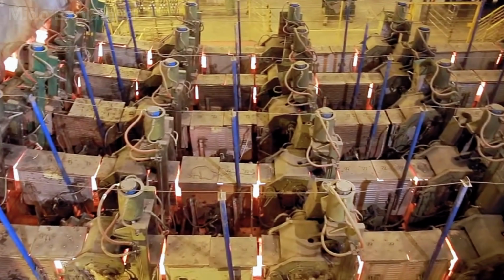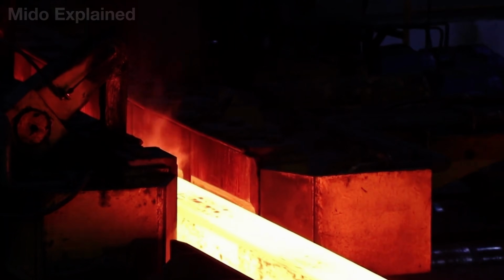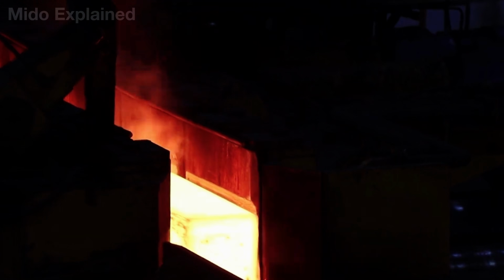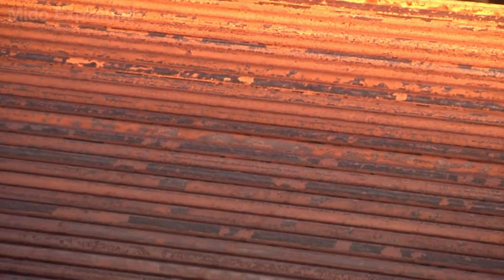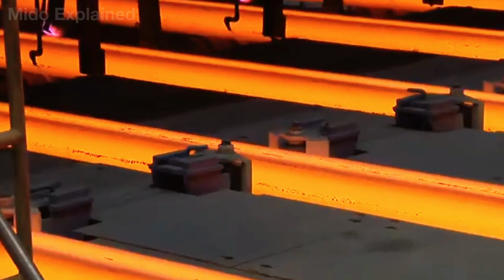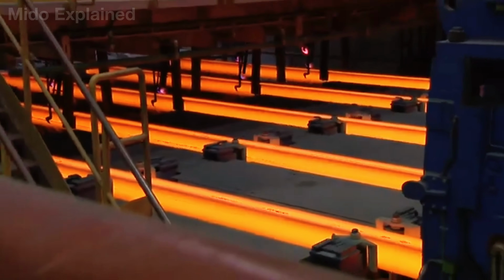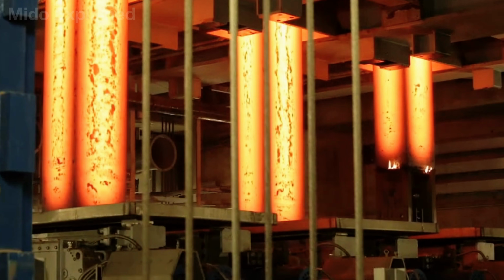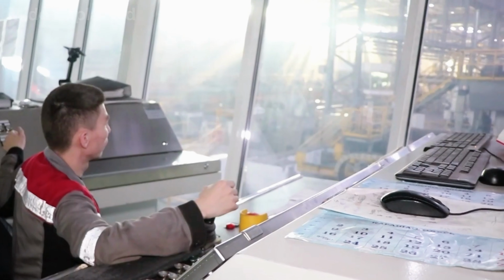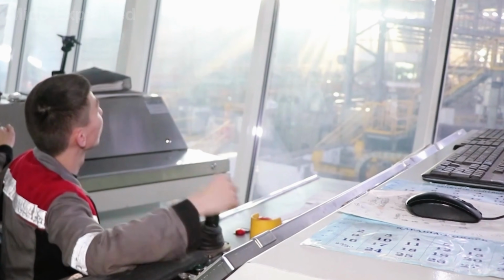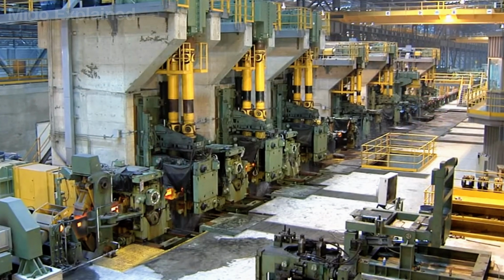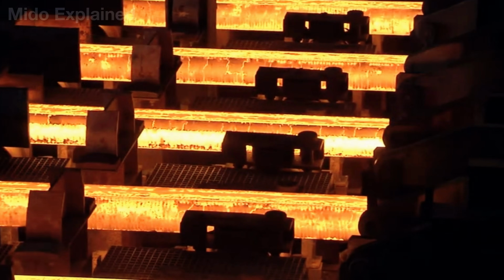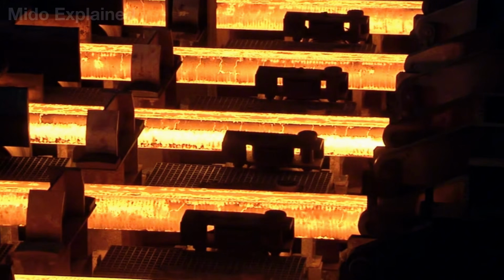If the temperature difference between areas is too large, the billet may crack or deform under pressure in the next stage. Once the required temperature is reached, the billets are removed from the furnace using an automated roller conveyor system hundreds of feet long. Along the way, they pass infrared temperature sensors, surveillance cameras, and most notably, a high-pressure water spray system that removes the oxide layer formed during the heating process.